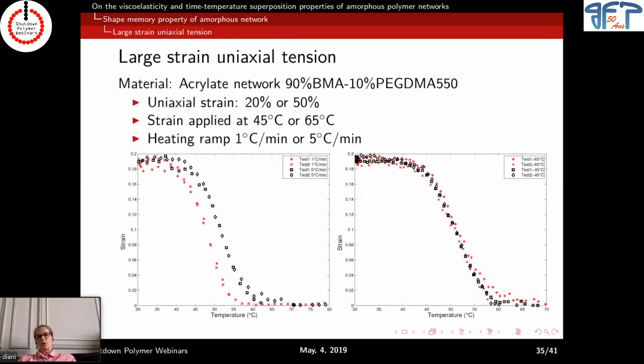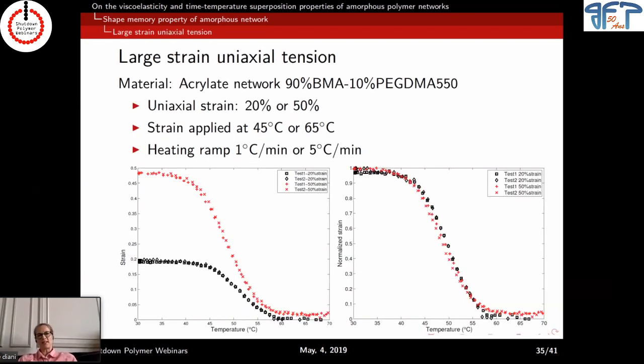We looked also at a large strain uniaxial tension test, because it gave us a little bit more versatility. So we could look at large strains of 20 and 50%. We could look at the temperature at which we applied the strain. So 65 basically for us was the rubbery state. 45 was the beginning of the onset of the viscoelasticity. We looked at the impact of the heating ramp, but more interestingly,